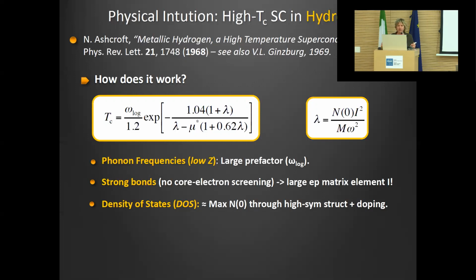The reason was that at the time when Ashcroft was writing, he was thinking about atomic hydrogen in some kind of BCC, HCP lattice, and these kinds of lattices typically have very steep peaks in the density of states. Then the second reason is a bit more subtle. You have this I. This I is a constant, sometimes called the deformation potential. This is an electron-phonon matrix element. It measures basically how much the electronic system is perturbed by the ionic motion.